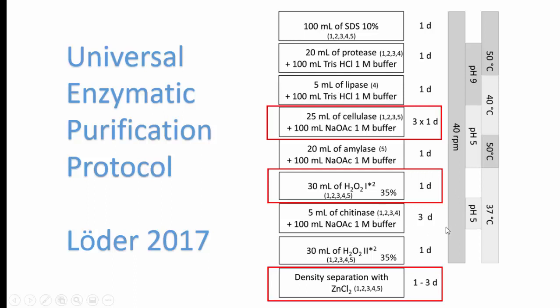So we chose it based on these 3 key characteristics, and in a slightly different order. Almost all the methodologies we encountered use some form of wet oxidation with peroxide, and a few of them used density separations using either zinc chloride or a calcium chloride. And when dealing with wastewater, cellulose is a huge burden. It's probably 90-95% of the problem that you're trying to address is the interference from cellulose.